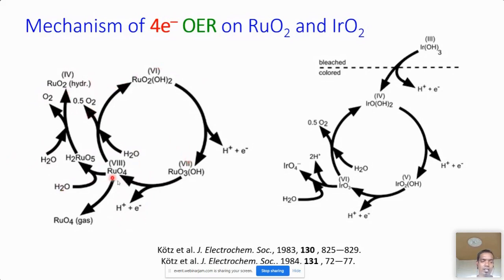But the problem is there's an additional mechanism by which this material can get depleted, which is the volatile nature of ruthenium tetroxide. This is a poisonous gas, so whenever you work on water electrolysis with this material, you should ensure there is no escaping of ruthenium tetroxide from the cell.